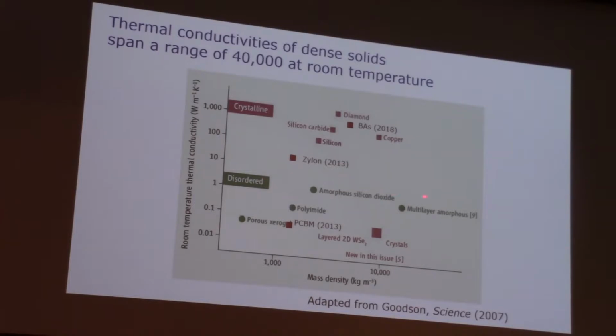And then we go into amorphous materials. 1 is a good number to remember. That's basically window glass. It has a thermal conductivity of unity in watt per meter Kelvin. Polymers typically have about 0.2 or so. And like I said, I'll talk about these numbers down here, which are about 0.05. This is an organic material. This is an inorganic material. For completely different reasons, they have thermal conductivities of about 0.05 watt per meter Kelvin, which is about twice the thermal conductivity of air.